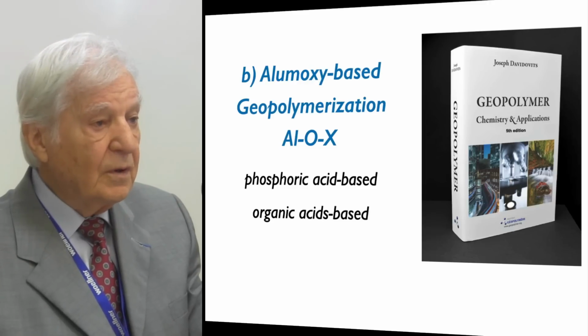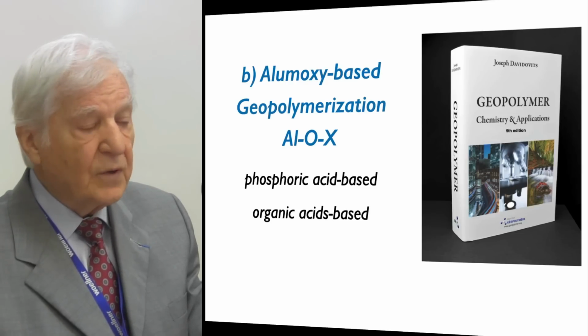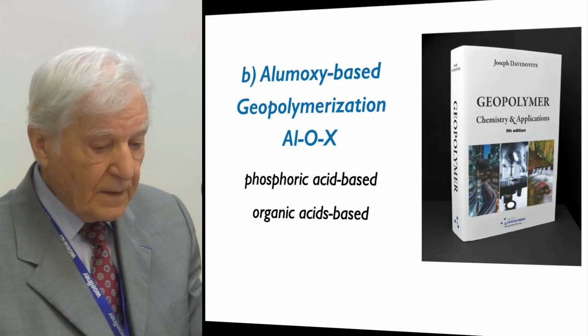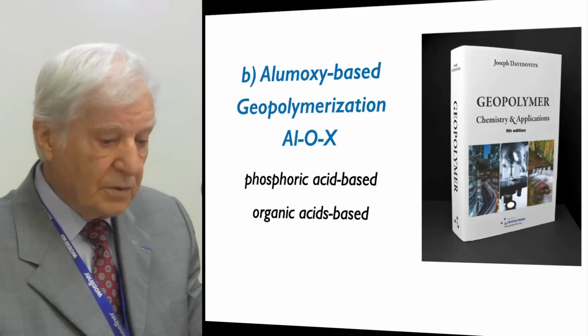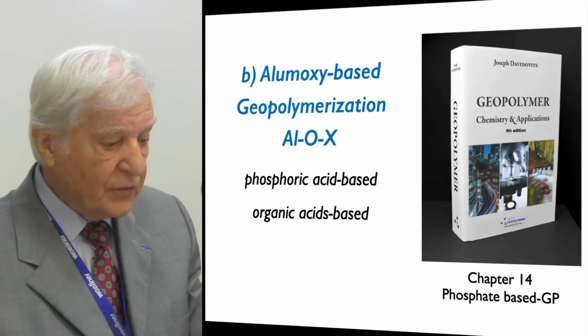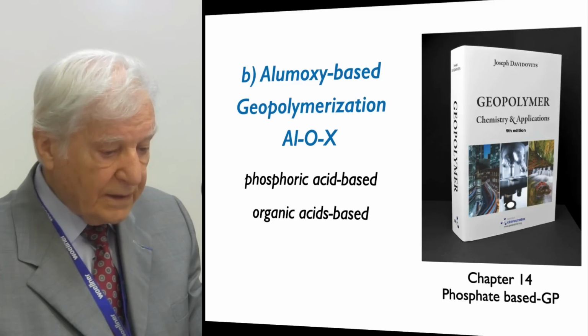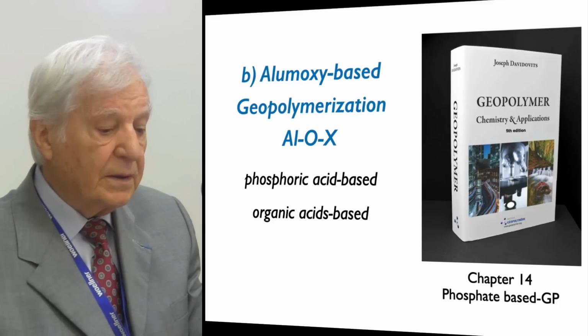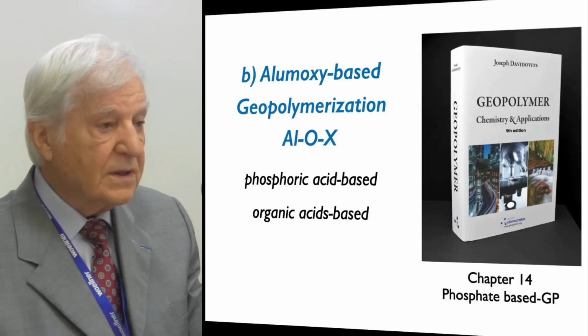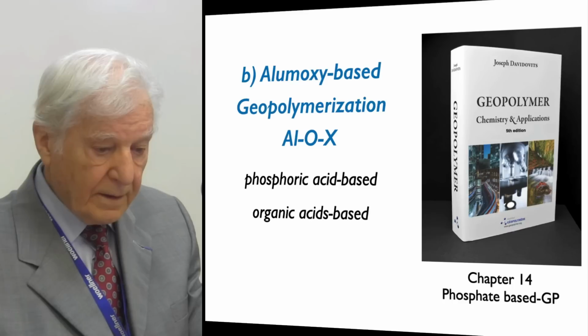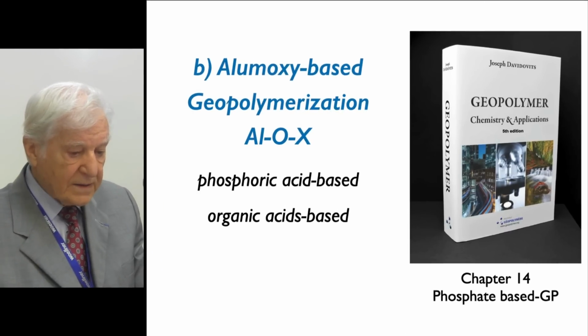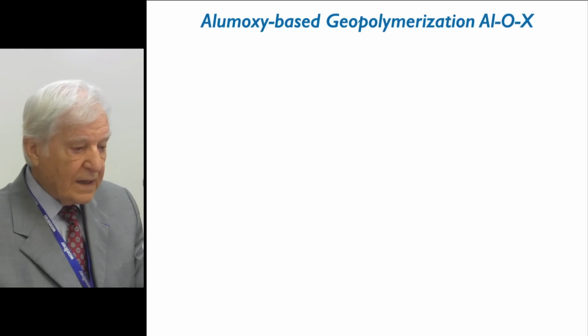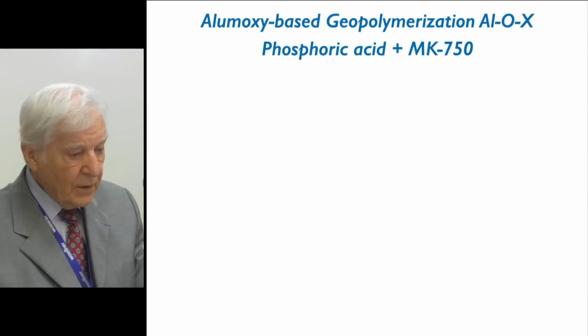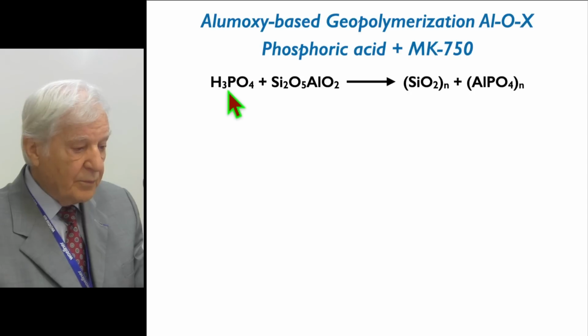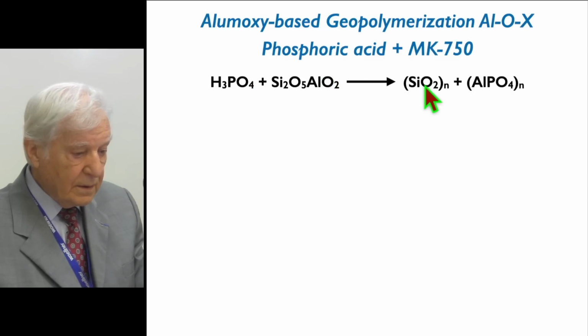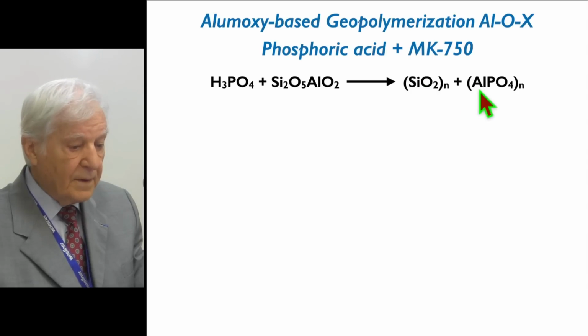First, SiO2 units. We know that metakaolin, when added to acid, the acid extracts the SiO2. Second, alumoxy units. For example, with phosphoric acid, we get the phosphate-based geopolymer that is explained in chapter 14. For organic acid, we don't have anything written so far. For phosphoric acid, for example, phosphoric acid reacts with metakaolin according to the chemical reaction: H3PO4, phosphoric acid, plus metakaolin yields SiO2 and aluminum phosphate.